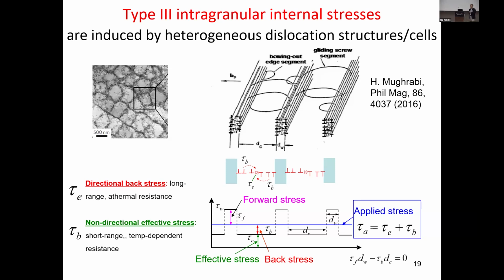geometrically necessary dislocations. In case you are not in the field, you might understand those geometrically necessary dislocations as positive and negative charges, right? If you have a group of positive charges, they actually will collectively produce a directional field. In this case, the directional stress field is what we call the back stress. And then the local dislocations also serve as obstacles, obstructing the dislocations. They produce the so-called effective stress.